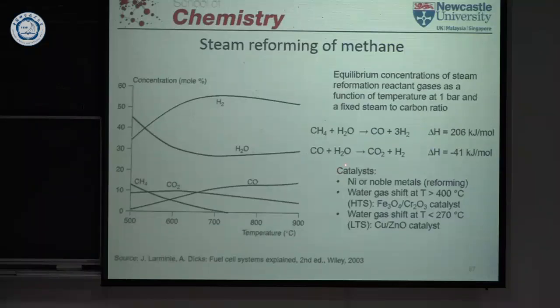So when you go to a high temperature, then essentially you get the left side, because it's exothermic, you drive it actually to this side. When you go to low temperature, you drive it to this side. Now, a typical reactor temperature, let's say for methane, you use something like 800 degrees as the typical reforming temperature. And then you can see here the different concentrations, and at about 750 you start having all the methane react. So you go to 750 to 800 because then you have complete reaction of the methane.